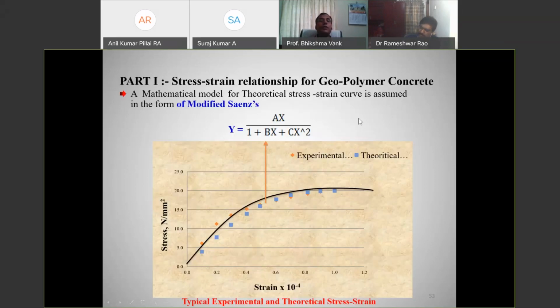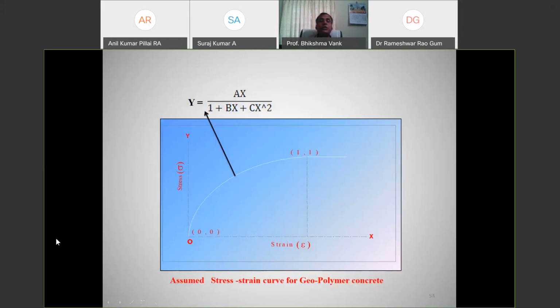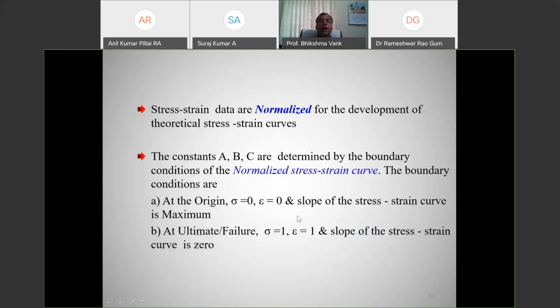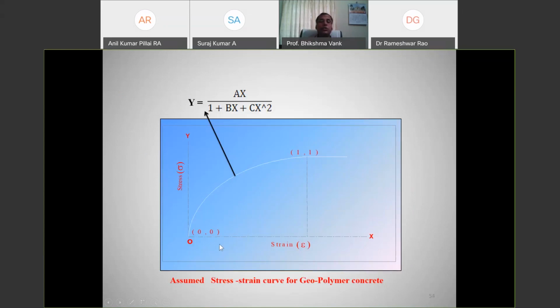Stress strain relation for geopolymer concrete, modified Sargin model we have taken. This is stress, this is strain of the concrete which we got experimental, theoretical, and we have developed an equation, y is equal to ax by 1 plus bx plus cx square, a parabolic equation for each grade of concrete, and this is normalized, non-dimensionalized to get a curve. Boundary conditions we have obtained for the curve, stress and strain, and the non-dimensional is 0, 0 initial value and 1, 1 final value. Intermediate values have been obtained.